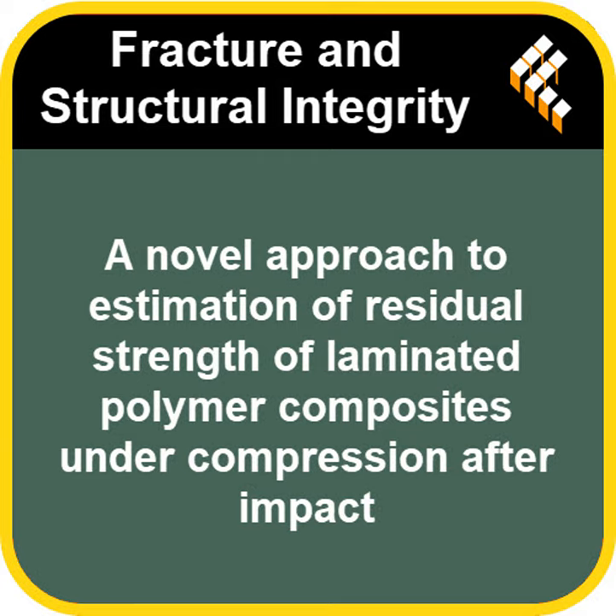And this corresponded to much larger areas of delamination and even actual fiber breakage right on the surface where the impactor made contact. And then at the high energy levels, 60 up to 100 joules, the impactor actually punched right through the specimen, what they call a breakthrough. But what's interesting is even after the breakthrough, the load didn't just drop to zero. It often increased again slightly as the impactor continued to push through and was slowed down by the surrounding, already damaged material. Huh. So it's not just a simple scale up. The type of damage fundamentally changes as the impact gets harder.